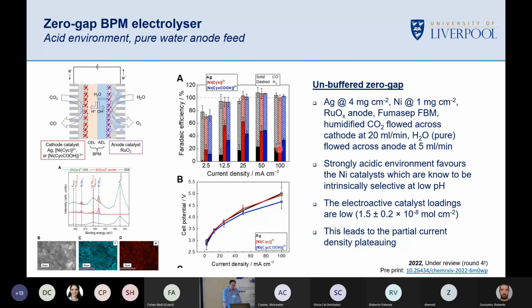The cyclam catalysts behave quite differently. So here we are at 12.5 milliamps per square centimetre, 25. We're getting in excess of 60% Faraday efficiencies for our cyclam catalysts. And actually, this is a time-dependent Faraday efficiency. If I look at very early times, it's up in the 80%. So our catalyst is working with really quite high selectivity.